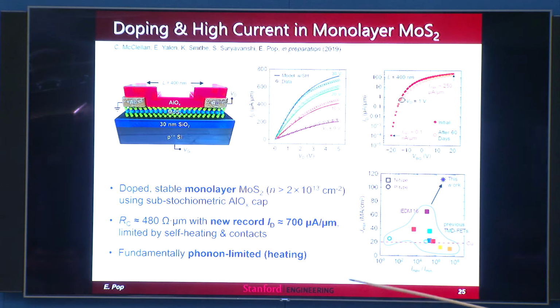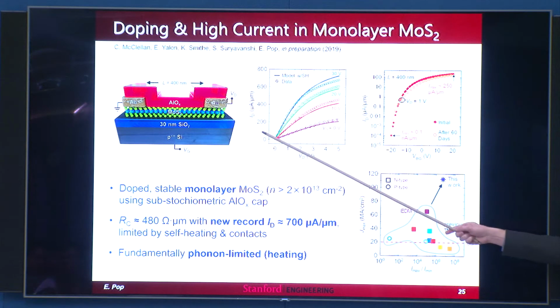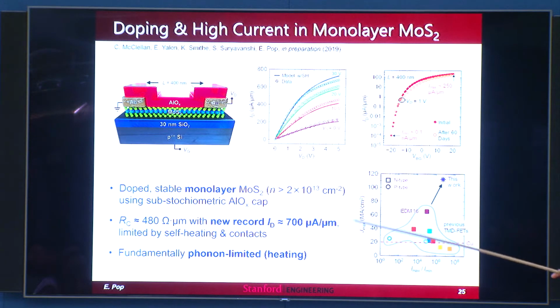And so by doing this, we've actually achieved record current densities of about 700 microamps per micron in these devices. And again, keep in mind, this is 700 microamps per micron through a 3-atom thick transistor. And the contacts have also improved to be just below half a kilo-ohm micron. And actually, if I replot the current density in units of megaamps per square centimeter, this is where we are right now for some of these devices. These numbers are huge, actually, for a 3-atom thick material, more than 100 megaamps per square centimeter. The electromigration current density of copper is about here, maybe even a little bit lower. So the current densities are actually quite high.